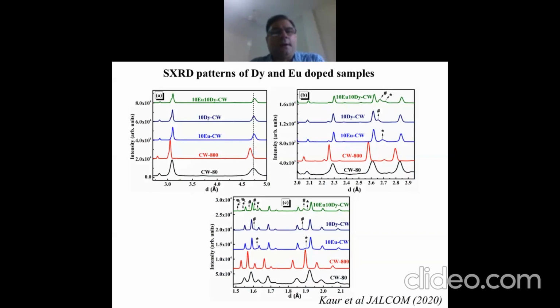These are the X-ray diffraction patterns. In the top graph on the left-hand side, the bottommost trace is of the calcium tungstate nanoparticle sample. You see broad peaks. Here along the x-axis, we have plotted d-spacing, not the angle 2 theta. The first sample is a nanoparticle sample with a particle size of about 35 to 40 nanometers. When you anneal the sample, the peaks sharpen because of the increase in the size of the crystallites, and the peaks also shift towards lower d values.